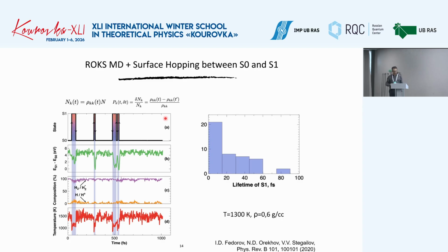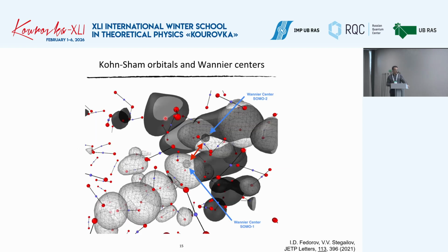So in our first work, we tried ROKS-MD with surface hopping between the ground state and the excited state, just to illustrate that the lifetimes of the system in thermal equilibrium could be up to hundreds of femtoseconds. So it is much longer than the time step in molecular dynamics. That's why we should resolve explicitly these hopping events. We cannot average them in molecular dynamics. And another main point is that in order to analyze how this solution evolves, we should use some localization method for SOMO orbitals, and for this purpose we use Wannier centers. That makes much more sense, gives much more clear visual information than the shape of Kohn-Sham orbitals.